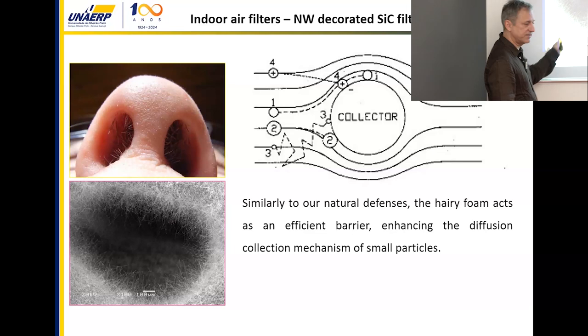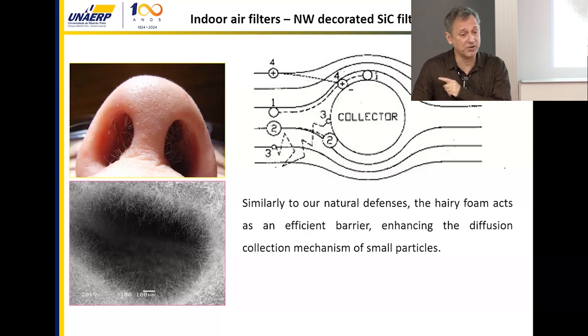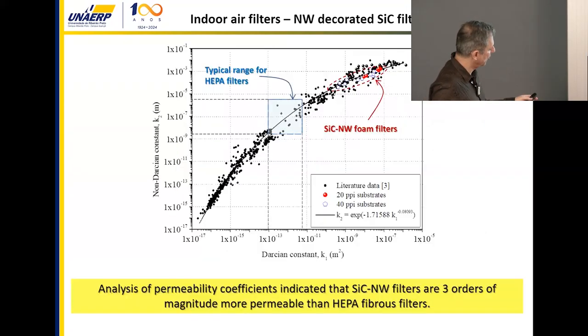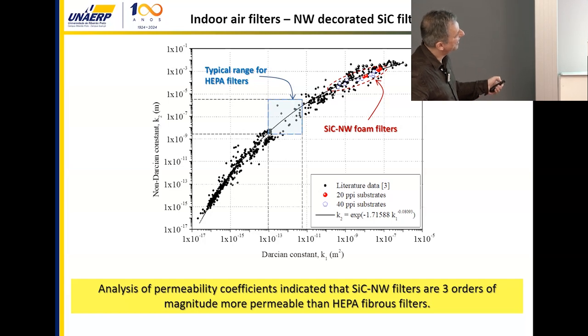So these particles kind of bind on the filament. Yes. Every time that a particle hits the filament, the nanowire, you have a collection of the particle. If you have a very large velocity, then you have the hit and the bouncing of the particle. You don't collect anymore. But in normal use, you have an enhancement of the collection. So just to let you know, the HEPA filters are here. And we got the silicon carbide with nanowire foam filters. The permeation level is almost 3 orders of magnitude higher, which is better. The idea is not, of course, using this as a mask, but using this as an air conditioning device to help the control of aerosol inside environments.